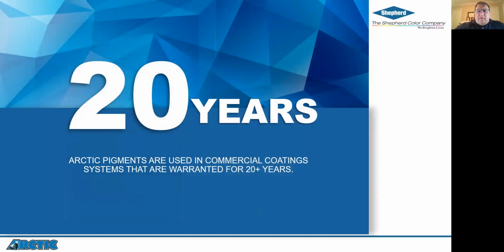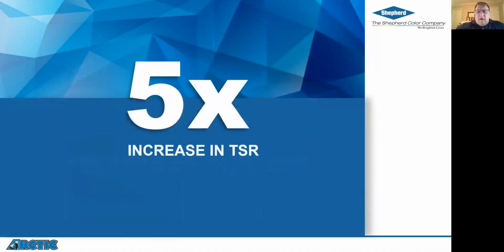So these are the kind of pigments that give the paints and coatings and plastics manufacturers the ability to have products that have life cycles of over 20 years. Sometimes they have 40-year warranties for these commercial products. And as we saw, standard black has around 5% reflectance. These infrared reflecting blacks have around 25 to 30% reflectance. So you're getting a 5 times increase in the total solar reflectance.